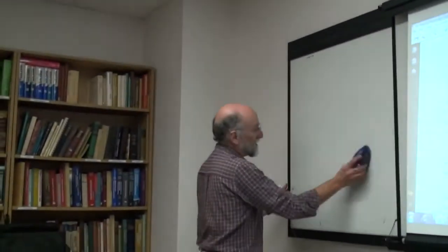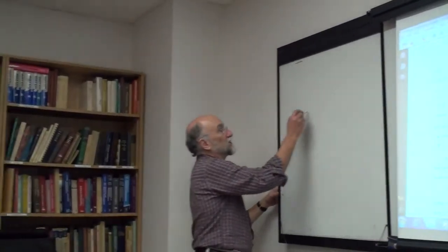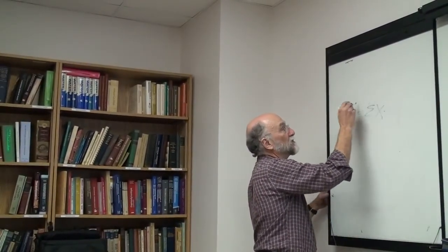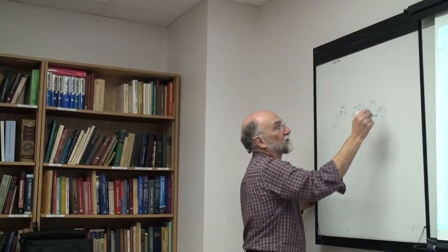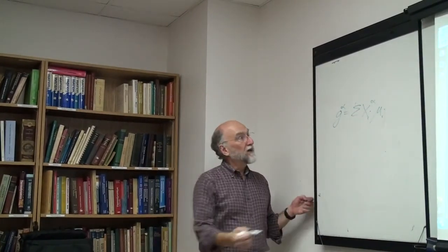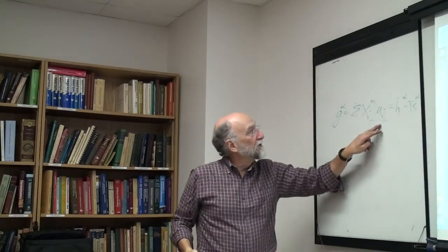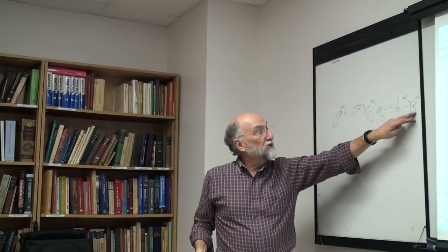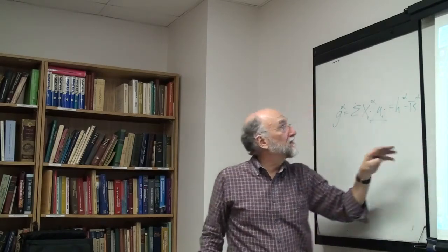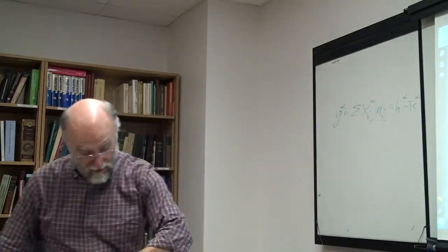If we're looking at the chemical potentials as the variables, the Gibbs energy of phase alpha is the sum over i of x_i mu_i, and that's equal to H of alpha minus T S of alpha. So if I've given all the mu's as variables, that gives me G. If I then choose S, well then H can be calculated. If I have all the mu's and S, I have H. Or vice versa, if I define H as my variable here, then I have S. All right, so those are all my variables.